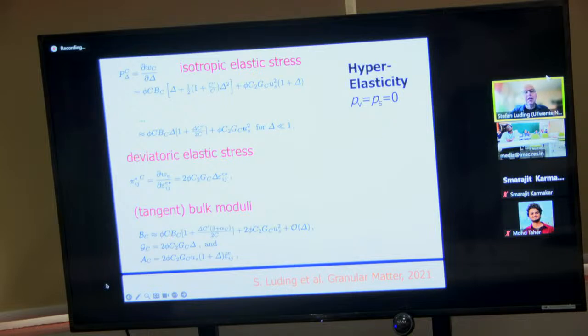Now, there are some other cases. You can go to hyperelasticity if you set the probability for plastic events to 0. Okay, and then you can write down all the theory. It's a little bit messy equations, but it's straightforward to write down all the theory terms in the syntax which I was introducing. Okay, and then you also will get the tangent bulk moduli like compression modulus, shear modulus, and there's an anisotropy modulus also, which is due to the cross-coupling between isotropic and shear events, isotropic and shear strains.